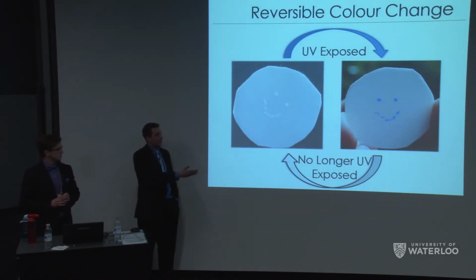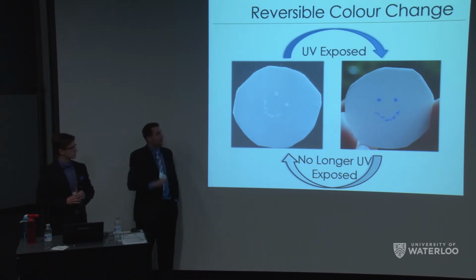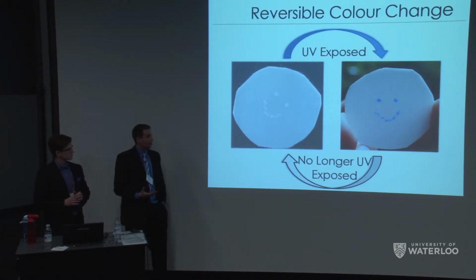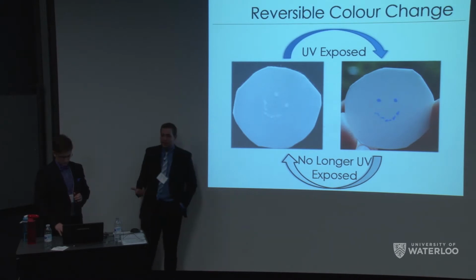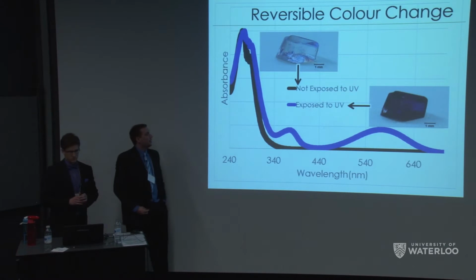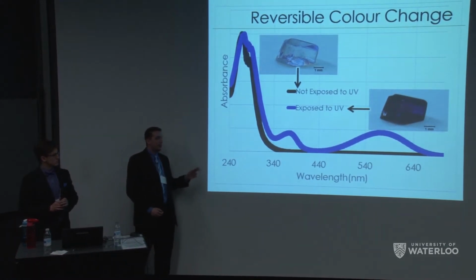Here we've actually drawn this on a surface. We've taken it outside, on the far left here where it's blue. It's a blue color change, it happens immediately in sunlight, and when we bring it back inside, where there's no more UV light and we're just in the presence of regular visible light, it changes back to white, again demonstrating that reversibility. And to talk a little more about how that's happening, here we have two UV absorbance curves.